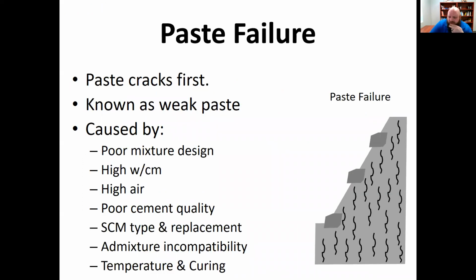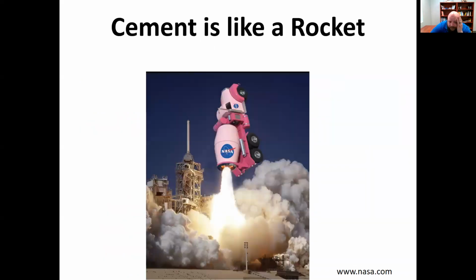Talk about a paste failure. You can see here, we've got these little bitty micro cracks everywhere on the cylinder. And so it's actually known to be a weak paste that's caused by poor mixture design, high water cement ratio, high air. Again, lots of different reasons why it's common.